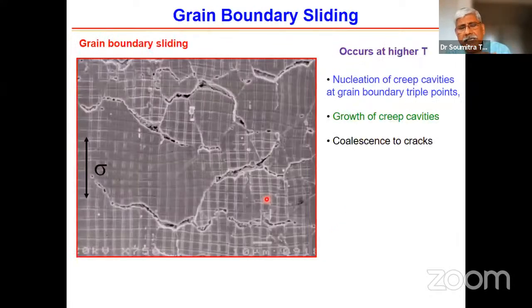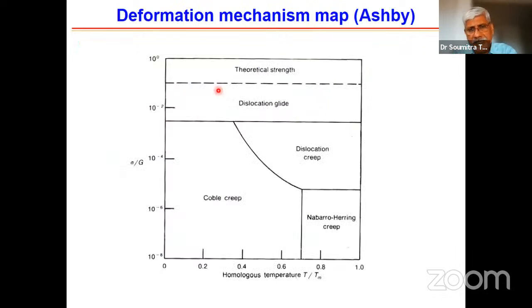And of course, when you reach the ending stages, you have a lot of creep cavities, you have a lot of grain boundary sliding, and crack formation, which ultimately grows and leads to failure. So you have to avoid this obviously. But can you tell at what stage of dislocation or diffusion you are non-destructively in order to quantify the damage? So this is the mechanism map for creep. You have Coble creep, Nabarro-Herring creep, dislocation creep, and dislocation glide.